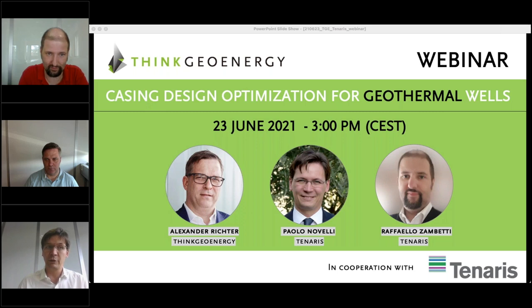One last point, where we see coatings extremely interesting is more on the low enthalpy field. Again, speaking in particular about Central Europe and Northern Europe, we see a lot of increase of projects focusing on the use of geothermal energy for heating purposes. In that case, the typical temperature is around 100, 120 degrees, and coatings are suitable in terms of temperature resistance.